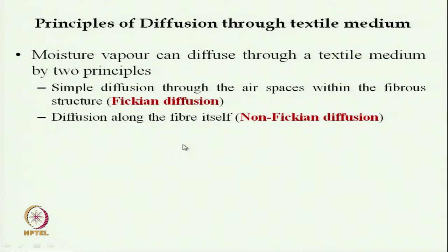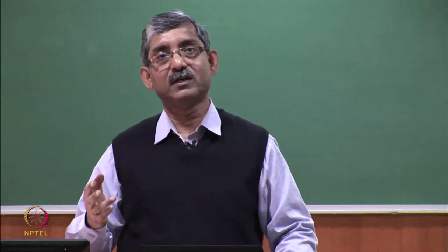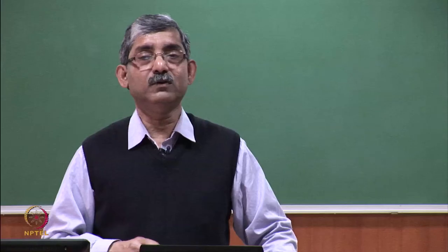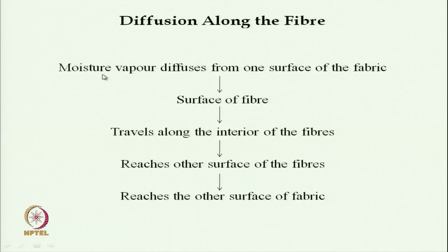And Fickian diffusion is almost instantaneous because the diffusion through air is very fast as compared to diffusion through a fibrous material. So, the stages are the diffusion along the fiber: moisture vapor diffuses from the skin to the first fabric surface, then the surface of fiber, and travels along the interior of the fibers. I am talking about here non-Fickian diffusion, then reaches the other surface of the fiber, then gradually reaches the other surface of fabric, as I have shown already. So, during the travel, these are the stages it covers.